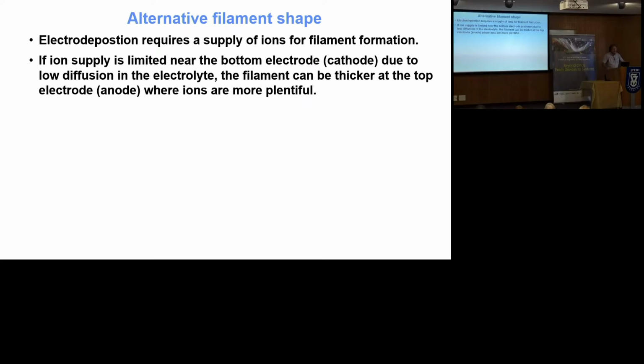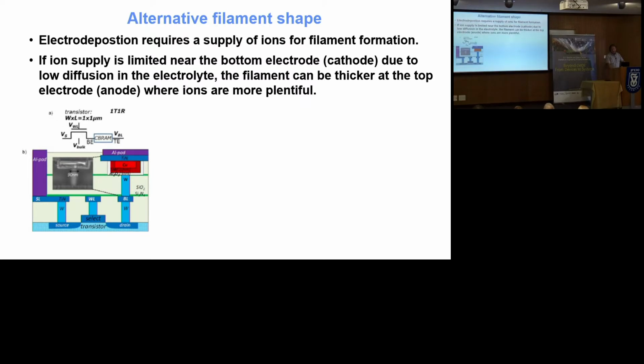I should say that we do tend to draw the filament, when we're explaining the technology, as a conical structure that basically starts on the cathode in the lower electrode there and then grows up. And as it does so, it fattens out at the first point that it grew at, and so you get more of a cone forming. But I should say that any electrodeposition process requires, of course, a supply of ions. And if you have a material that is a low diffusivity material as far as the ions and the metal are concerned, you can actually reach a situation where there are a lot more ions available for the reaction near the top electrode than near the bottom electrode, and it inverts what you see with the filament. And there are some examples of that being shown in the literature.